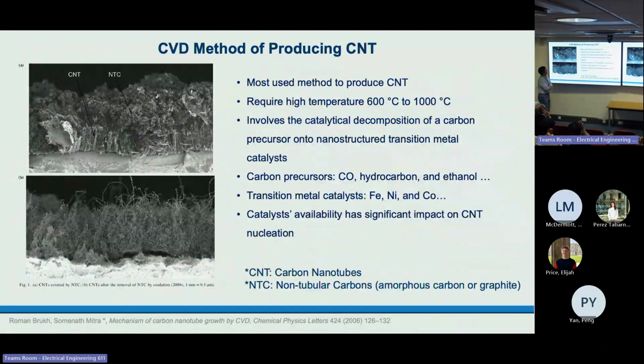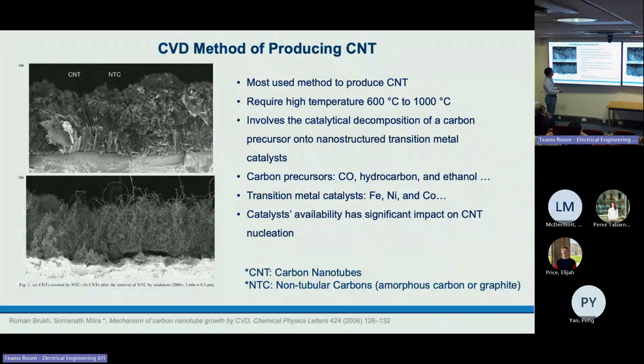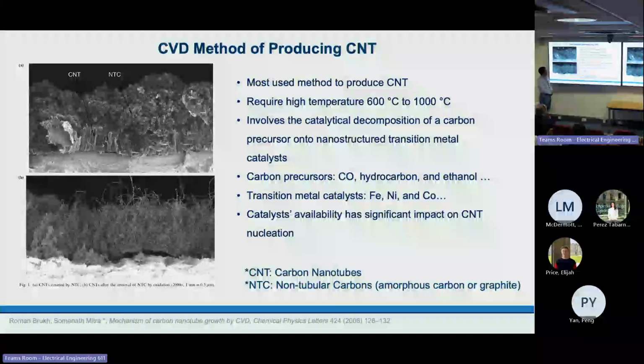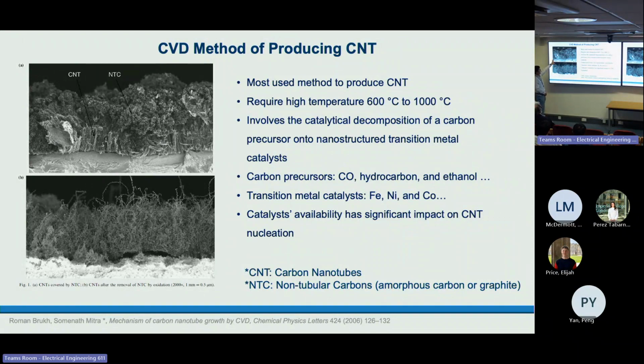As I said, the chemical vapor deposition (CVD) method is the most commonly used method to produce carbon nanotubes nowadays. It requires high temperature, up to 600 to 1,000 degrees, and it involves the process to catalytically decompose carbon precursors such as carbon monoxide, hydrocarbon, or ethanol onto a nanostructured transition metal catalyst such as nickel, iron, and also cobalt. So the catalyst availability has a significant impact on the CNT nucleation and the growth step, as we can see from the diagram on the left.